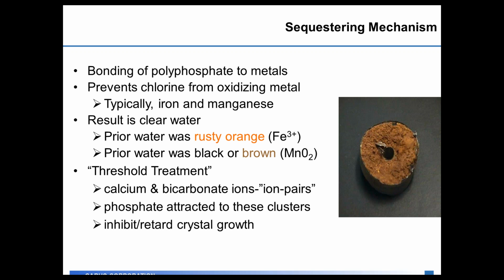Sequestering mechanisms. So these are the bonding of a polyphosphate or a condensed phosphate to the metals that are in the water. The idea here is you prevent the chlorine that you feed for disinfection from oxidizing the metal that's in the water to begin with. Typically what you're focused on is iron and manganese. The result with sequestering is if you had iron, the prior water would be rusty orange once you add chlorine. If it's manganese, the prior water would be brown at low levels or black at higher levels in the distribution system.